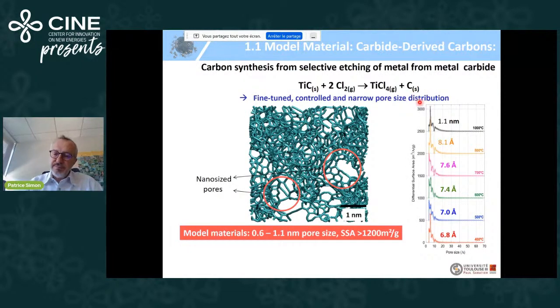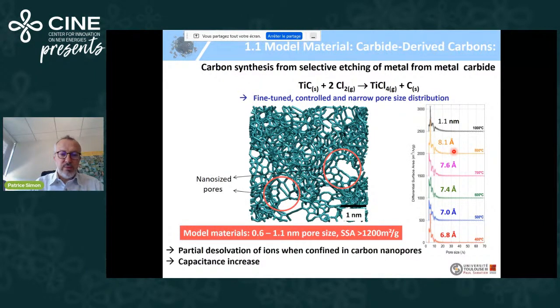And these are some examples of the pore volume versus the pore size. It's the pore size distribution for carbons, CDC, prepared at different temperatures. If you do the chlorination at 600 degrees, you see you have a very nice narrow distribution at 0.74 nanometers pore size. And if you use 800 Celsius degrees, then you have a mean average pore size of 0.8 nanometers. So we prepare like that a series of model materials with a very narrow pore size distribution to understand how ions are going in and out of these pores.